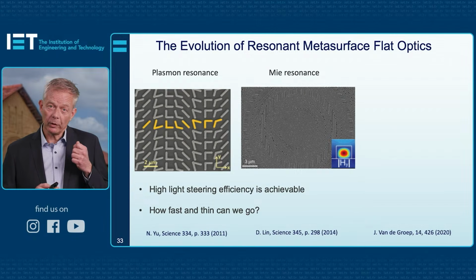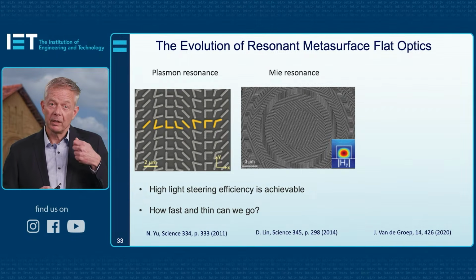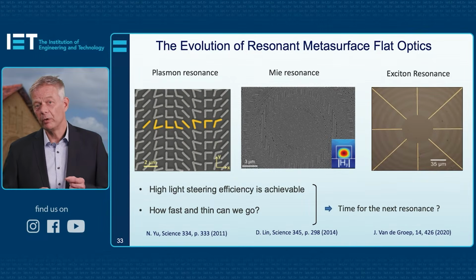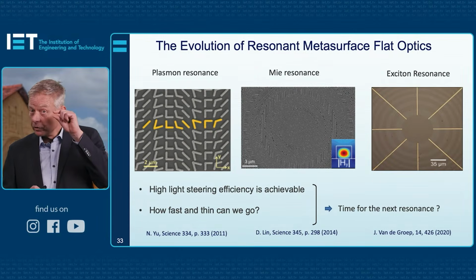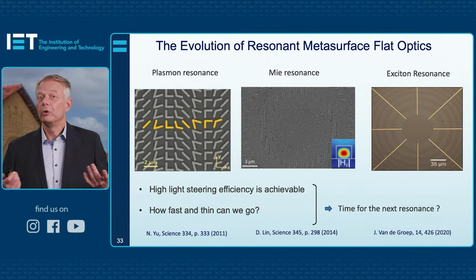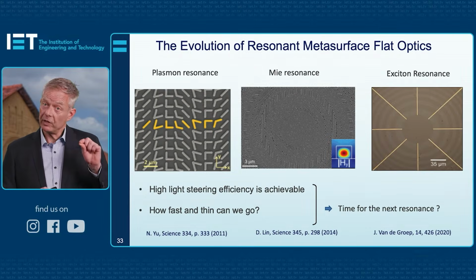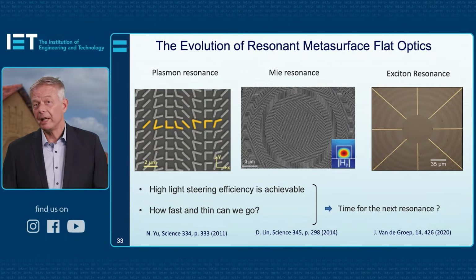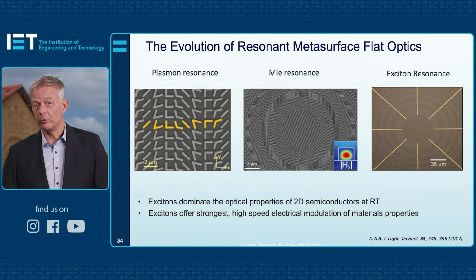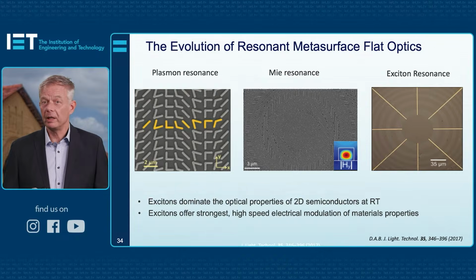So wouldn't it be wonderful if we could make things that tune fast and possibly even go to very thin scales? In our group, Jorik van der Groep nicely showed that if we go to the atomic scale, new opportunities come along when we make semiconductors so thin that they start supporting very strong, what are called exciton resonances. I'll discuss these more, but it turns out that these material resonances, excitons, dominate the optical spectrum in the visible. They produce very nice sharp peaked structures, and they offer some of the fastest light-matter interaction that can be tuned that we know of in optics.